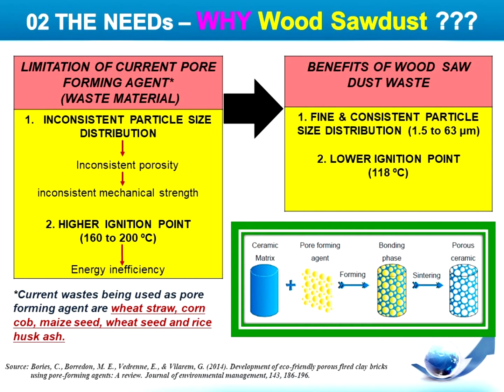Ladies and gentlemen, why wood sawdust? What is the function of the wood sawdust in porous ceramic production? The wood sawdust acts as a pore-forming agent to induce the formation of a well-controlled level of internal porosity in the porous ceramic. Subsequently, the pores will reduce the thermal conductivity of the ceramic, contributing to the thermal insulating properties.